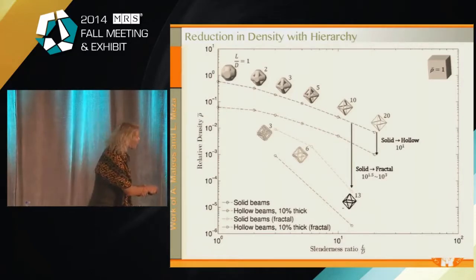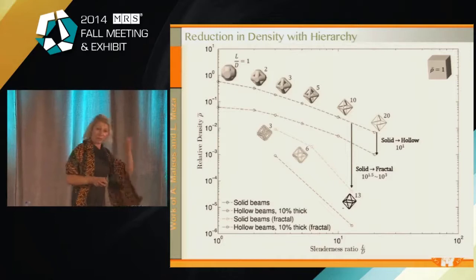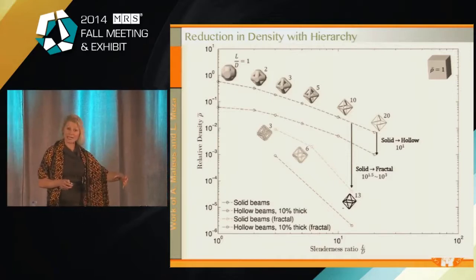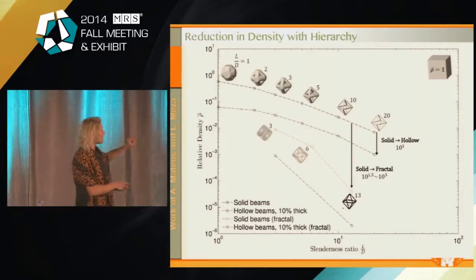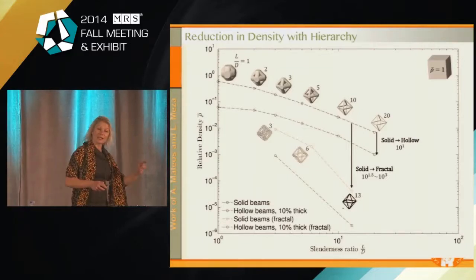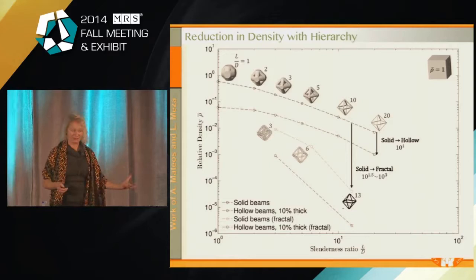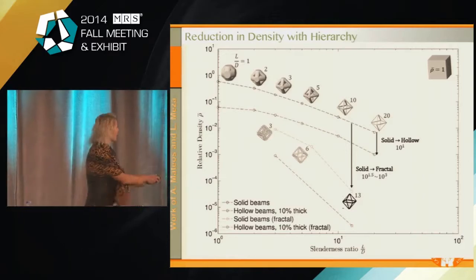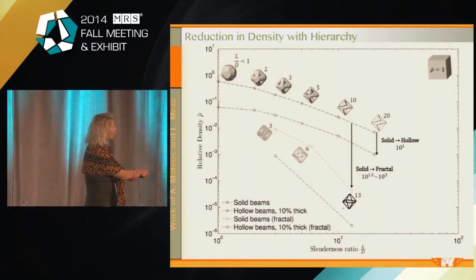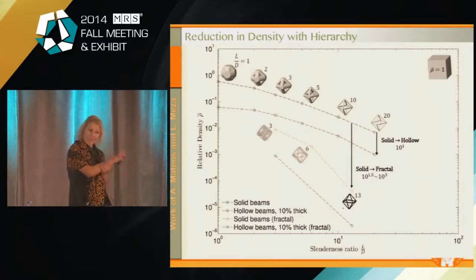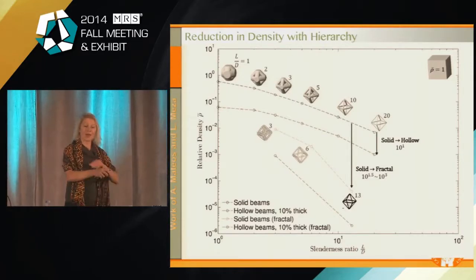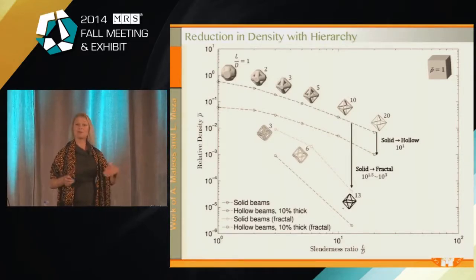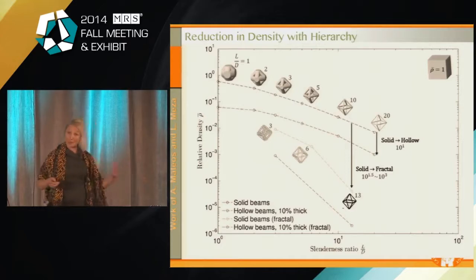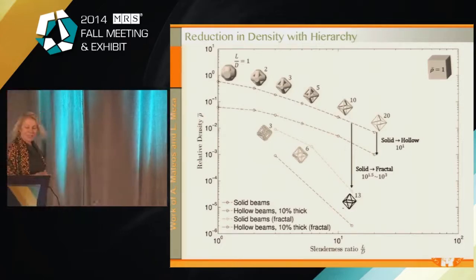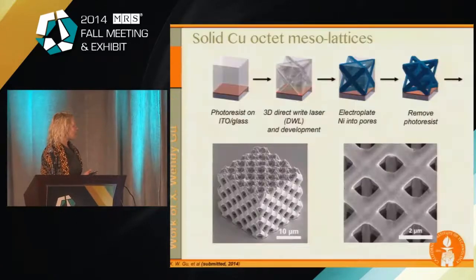And then what else you can do is, instead of each individual beam being a hollow tube by itself, which can shell buckle, we can populate each individual beam with a self-similar structure. It doesn't have to be self-similar, but we could do it in a self-similar way and also hollow these out. And that buys you 2 more orders of magnitude. So you can design your structures to be 100,000 times less dense just by architecting these, without any sacrifice in strength. Wouldn't it be awesome if we could mass produce these and make airplanes out of these? Yeah, so this is a pretty powerful way to approach material creation.